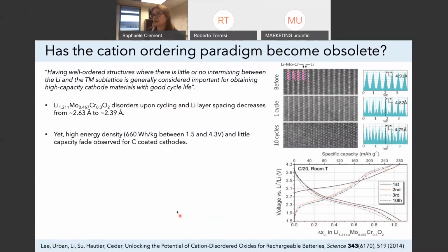And so this work started with a nice paper by the Ceder group. And what they made here, they made a lithium molybdenum chromium oxide compound as a layered compound initially. And you can see it from the STEM images shown here. So you start with a really nice ordered compound where you have these lithium layers in dark and the transition metal layers in lighter colors. But as soon as you start cycling it, the material disorders. And so after one cycle, you can see disordering here, which becomes a completely disordered structure after 10 cycles.